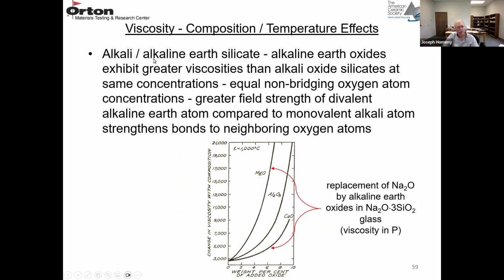And then the alkaline earth silicates, they can exhibit a greater viscosity than the alkali oxide silicates at the same concentration, and equal non-bridging oxygen atom concentrations. So the greater field strength of these divalent alkaline earth ions, like Ca2+, compared to the monovalent single charge alkali atoms, tends to strengthen the glass network.